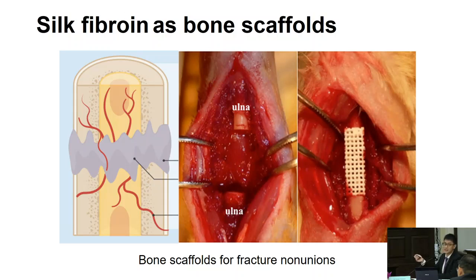So what we need is the bridge that connects this piece of the bone with this piece of the bone. And the way that the doctor does it is to put a bone scaffold into the place. So that allows communication between the two pieces of the bone, right? I did a very similar thing by using silk fibroin to make a bone scaffold. And I hope that the Thai silk fibroin can be made into this scaffold and then put into a bone fracture to see how fast the bone can heal itself.